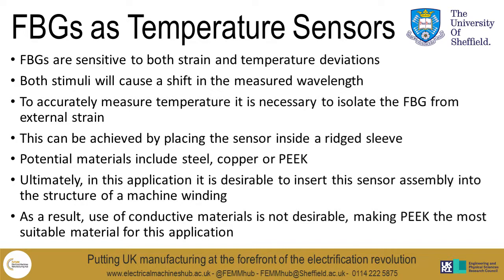So in order to use an FBG as a temperature sensor, there are a few things that need to be taken into consideration. The most important of which is that because an FBG is sensitive to both strain and temperature, both stimuli will cause a shift in the measured wavelength. So in order to accurately measure a temperature, it's necessary to isolate the FBG from the external strain which could be applied to it. This can be achieved by placing the sensor inside a rigid sleeve, and potential materials for this could include steel, copper or PEEK. Because the application we're looking at ultimately is in and around machine windings, it's desirable to use a sleeve which is an insulator rather than a conductor. So as a result of this, we believe PEEK is probably most suitable for our particular application.